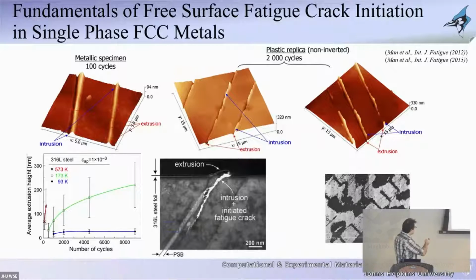But what you're seeing here basically is the surface. They reconstructed the surface roughness as the number of cycles increase. So after 100 cycles, you start seeing these bands that are forming on the surface, these basically intrusions and extrusions on the surface. As the number of cycles increase, you can see basically that these extrusions become higher and the intrusions become higher. And then eventually, this is a TEM image right around one of these ledges that have formed, these extrusions that have formed, and you can see that these cracks start initiating and eventually they propagate.